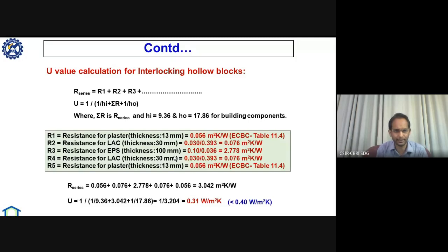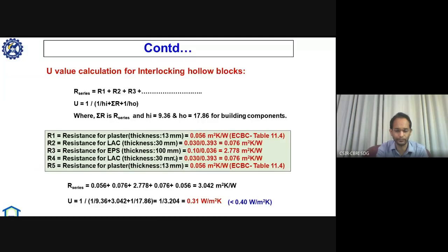Our main purpose was to optimize for U value. As you can see here, in the ECBC code, the Energy Conservation Building Code, revised version published in 2017 for composite climate, like the Roorkee area which comes in composite climate, our main target was to achieve a U value of 0.40. Till now we have achieved a U value of 0.31 watt per meter square Kelvin, and we are targeting to reduce it further.